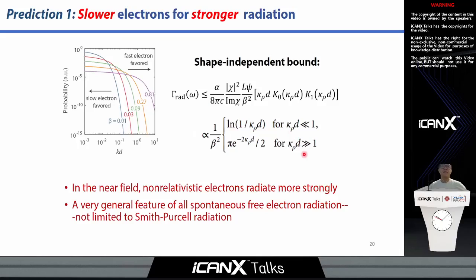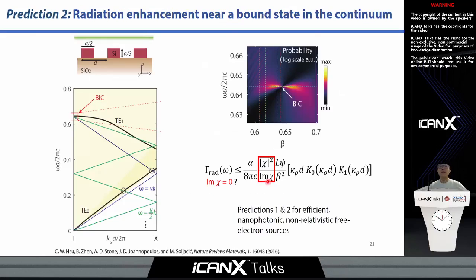So a second prediction is that there is an apparent divergence of our upper limit in the limit of lossless dielectric material. And we show that this is not a pure mathematical peculiarity. Rather, you can realize this situation by coupling free electrons with optical bound states in the continuum, which gives you enhancement via the infinite quality factor as well as the outcoupling capability. We do a numerical simulation to confirm this prediction by varying the electron velocity, and we show that there is indeed a divergent emission probability near these BIC resonances. So taken together, both predictions 1 and 2 show that it is possible to realize efficient nanophotonic sources based on non-relativistic electrons.